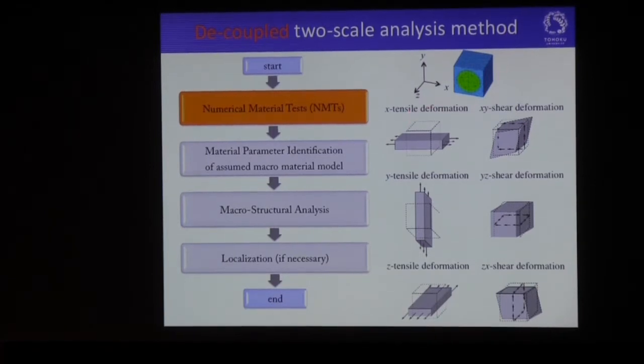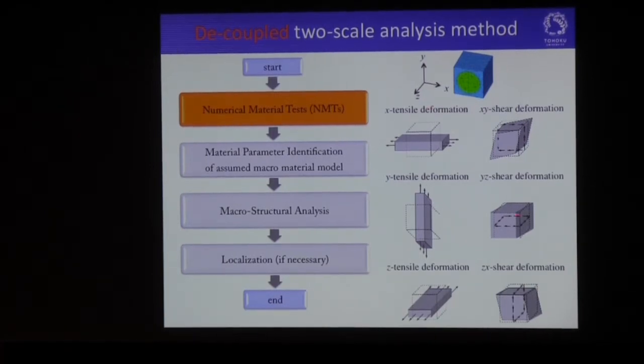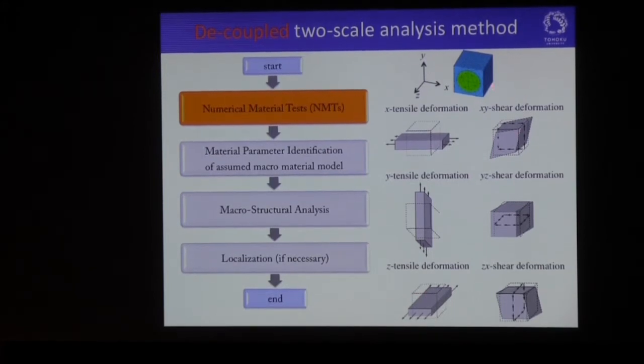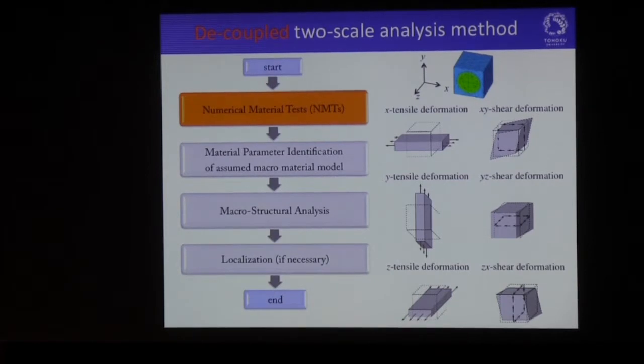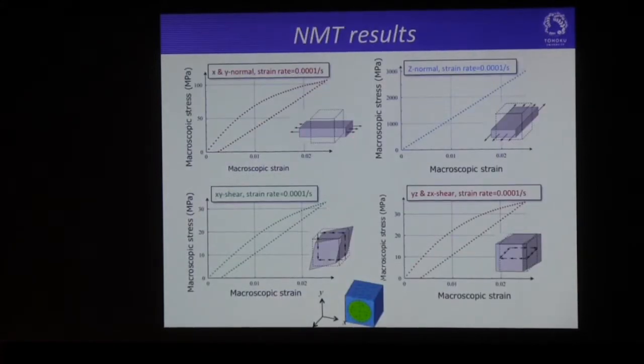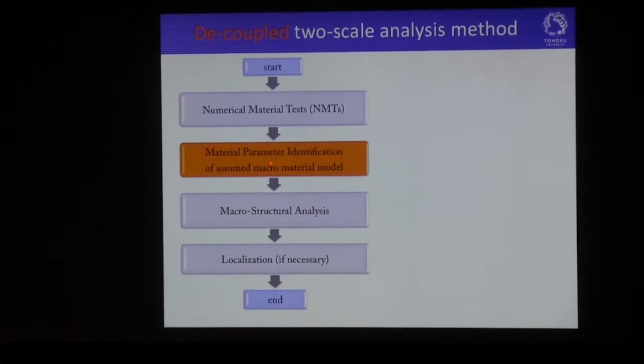That is, we can apply these 6 patterns of macroscopic deformation to the unit cell here in order to obtain the macroscopic mechanical behavior. This shows the numerical material test result. This shows the actual response in the X and Y direction, with the Z direction. These are the shear responses of the unit cell. As you can see, this macroscopic response well reflects the unit cell geometry here. Then let us move on to the next step.